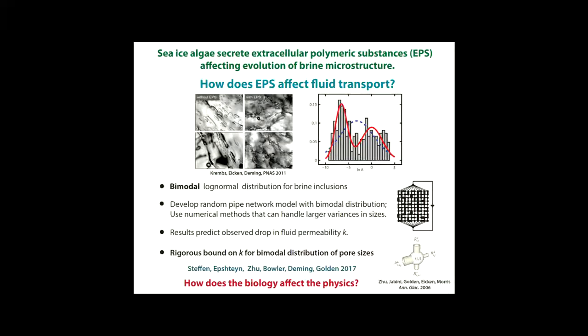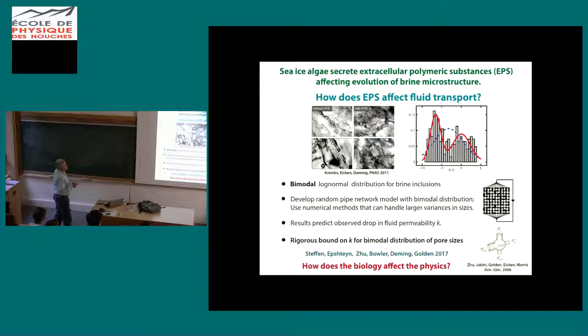As I mentioned before, sea ice algae secrete this goopy algal mucus, extracellular polymeric substance, EPS, which then affects the evolution of the brine microstructure. Here's the brine microstructure without EPS, and then it starts becoming fractal and all sorts of interesting. It screws up the way that salt moves in and out of the boundary between the ocean and the ice. And so we go from a classic log normal distribution for the regular brine inclusions in sea ice to a so-called bimodal log normal distribution.